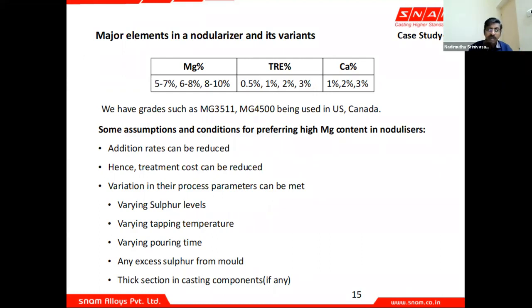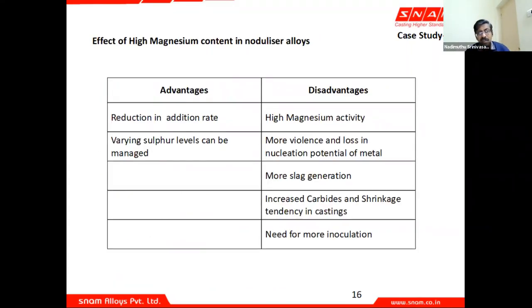So these are the assumptions for the foundryman when they decide, give me a higher percentage of magnesium alloy, right? But look at it, when you're going to increase the tapping temperature, pouring time, and for that particular reason, you are going to use a higher magnesium alloy, what happens? So the advantages, as I said, are what the foundryman assumes when he wants to place an order for a higher magnesium alloy. Fine, sir. And yes, your sulfur percentage could be varying. So you feel, I need more magnesium for desulfurization and the balance should be available for nodularizing. Perfectly right. But the disadvantages are you have a high magnesium activity, which means you're going to get more violence, more loss,